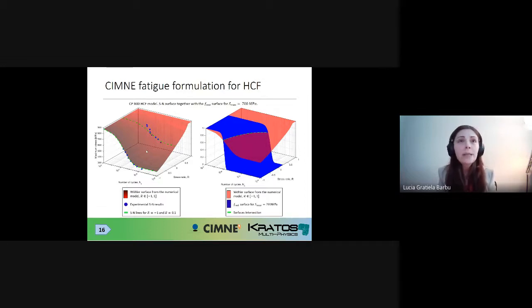This means that the stress state will be altered at those specific integration points inside those specific finite elements. This means that even if you begin with a stress ratio, for instance, of -1 or 0.1, you will have points that throughout the nonlinear process will change, will go away from that SN curve, which is specific for -1. If you have a model which only takes into account discrete SN curves, you are going to be in an indetermination if you are going away from that specific SN curve. This is why it's important to have a continuous, well-defined surface of stress number of cycles curve. And this is what we are doing inside our formulation. Here you can also see, for instance, what the reduction surface looks like when you intersect it with the SN surface for a specific level of maximum stress of 700 megapascals.